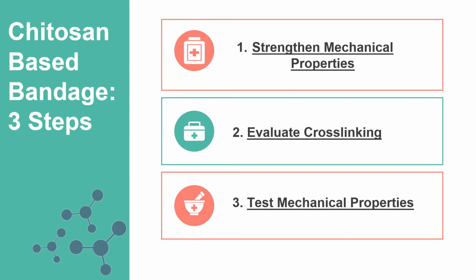We would like to note, however, that the cross-link material was brittle when dry, but when placed in water was hard to rip with our fingers. We suspended the mat in water and it did not dissolve within 7 days, whereas before cross-linking, the material dissolved within seconds. Thus, we can expect that the mechanical properties of our material would have been sufficient given our expected results of it being up to 90% as strong under tensile force as a piece of standard gauze.